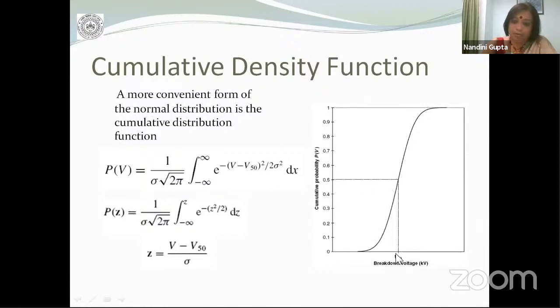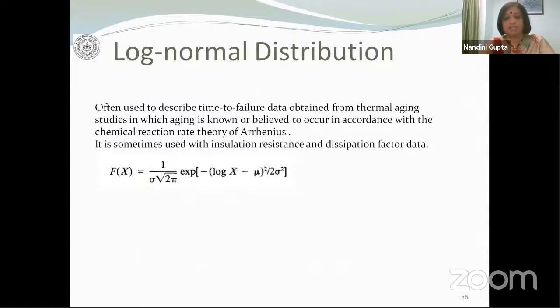So when I take this value, breakdown voltage V50, it means that at that particular voltage, the cumulative probability of failure at V50 or any value lower than V50 is 50%. And that is what I am interested in. For example, when we perform insulation coordination and look at the probability of overvoltages, we use a probability distribution function. But when we look at the probability of insulation failure, we look at the cumulative density function. So depending upon the physical significance of the random variable, we have to choose whether to look at the probability distribution function or the cumulative density function.